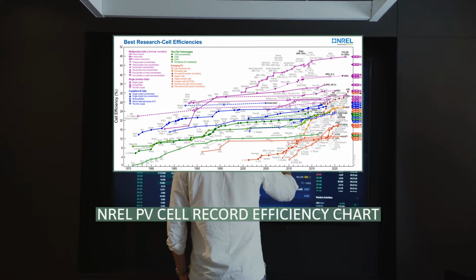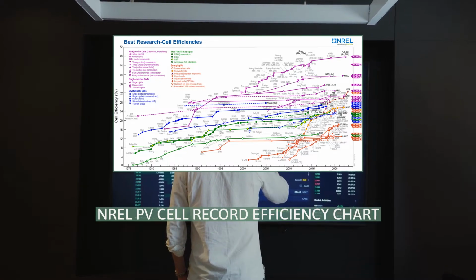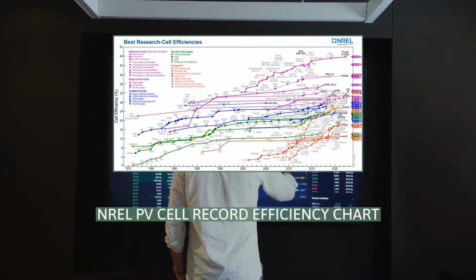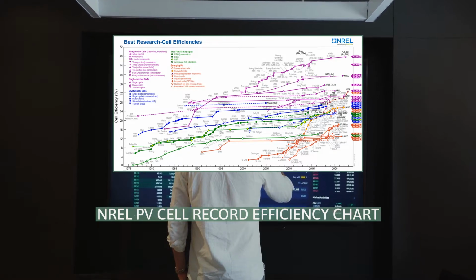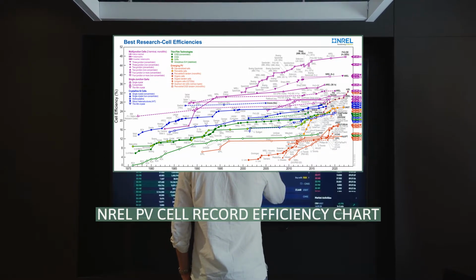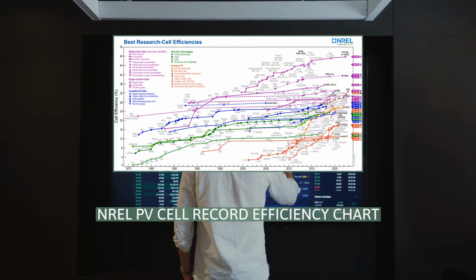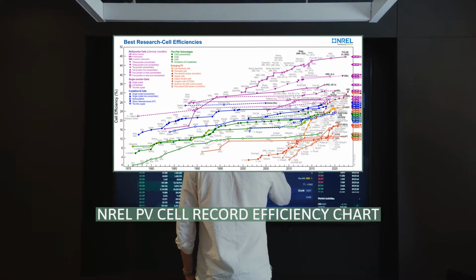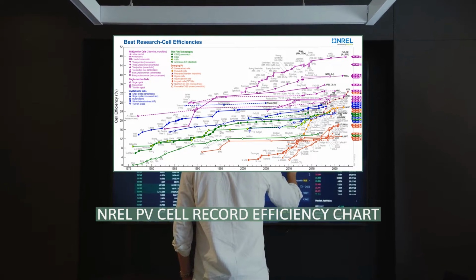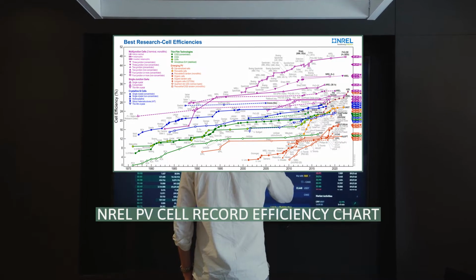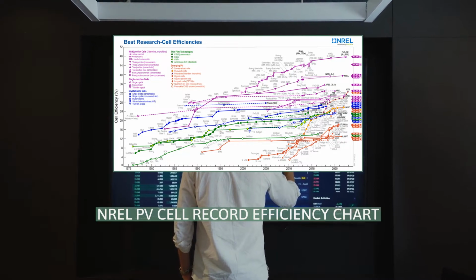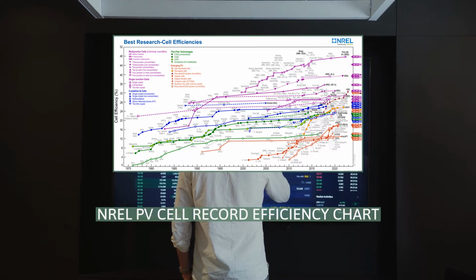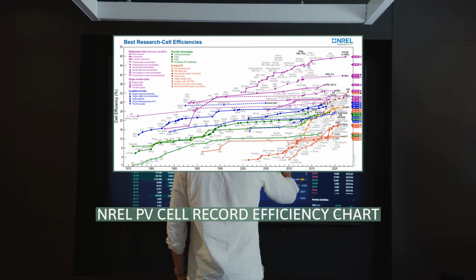As a result of this rotation, the electrical doping and contacts that were on the face of the wafer are located at the edges of the sliver, rather than at the front and rear as in the case of conventional wafer cells. This has the interesting effect of making the cell sensitive from both the front and rear of the cell, a property known as bifaciality. Using this technique, one silicon wafer is enough to build a 140 watt panel, compared to about 60 wafers needed for conventional modules of the same power output.